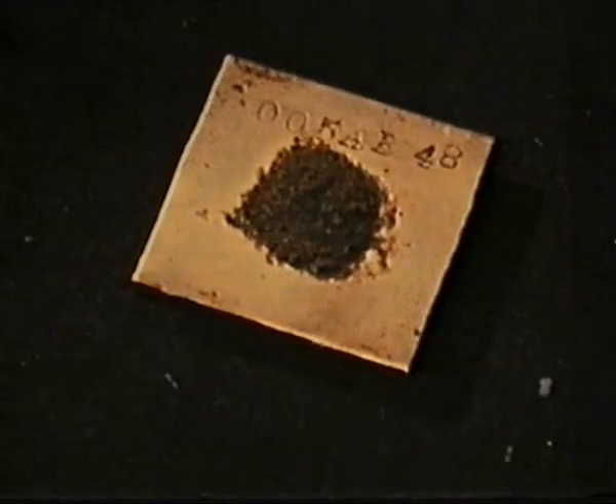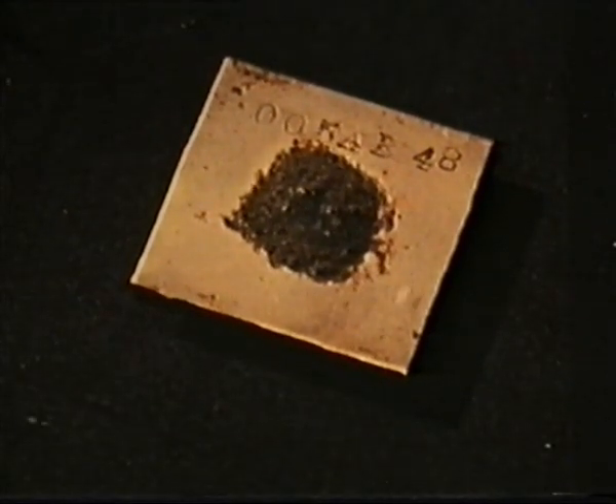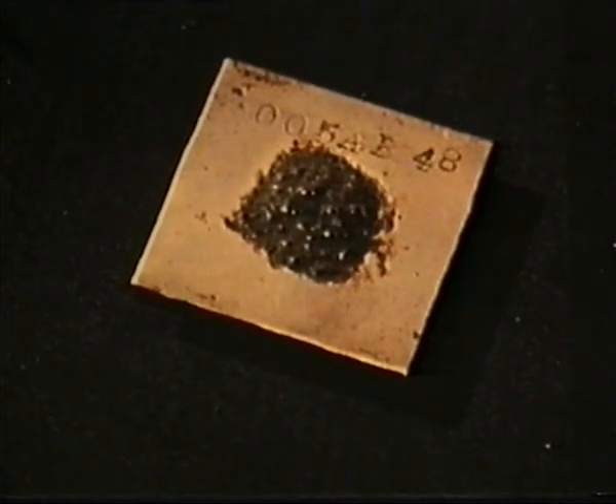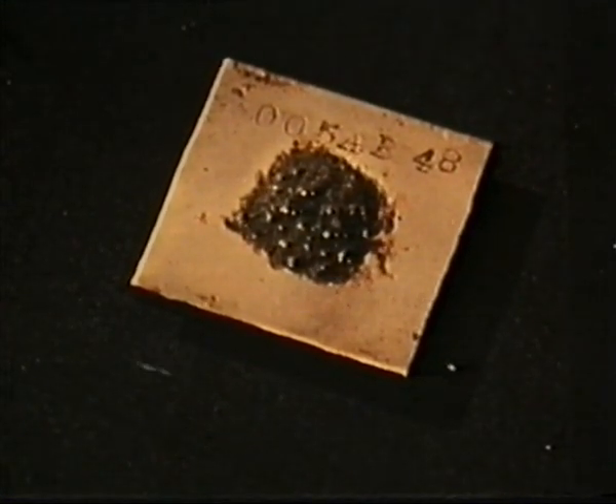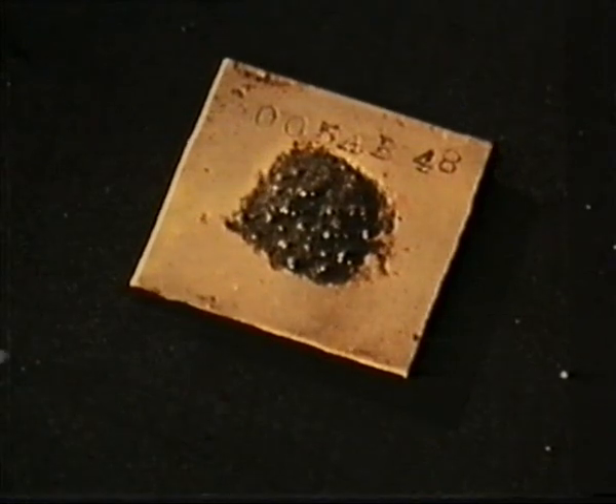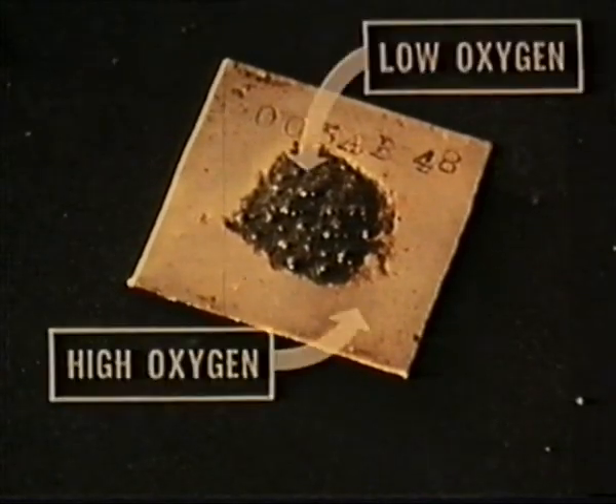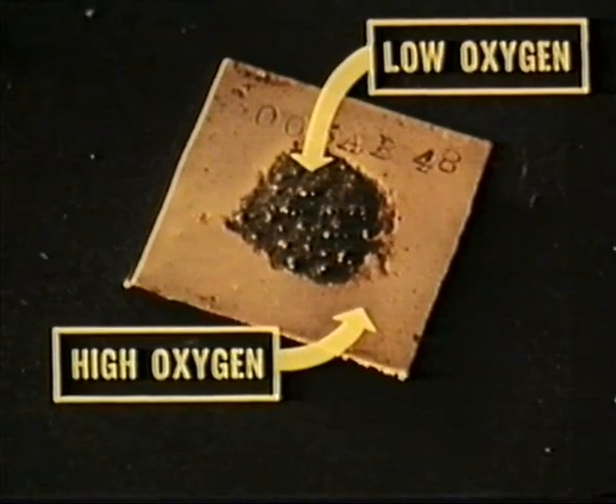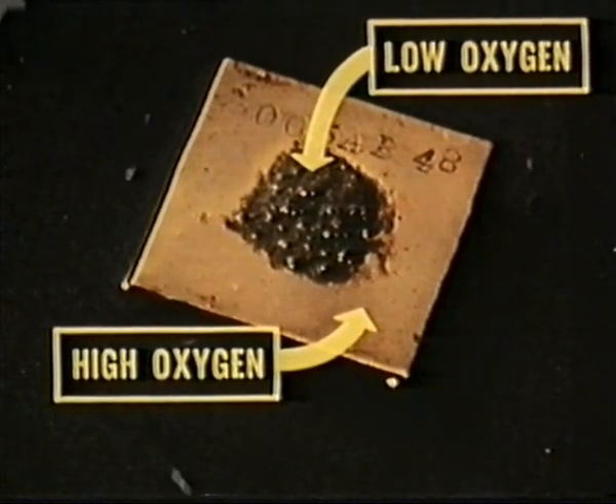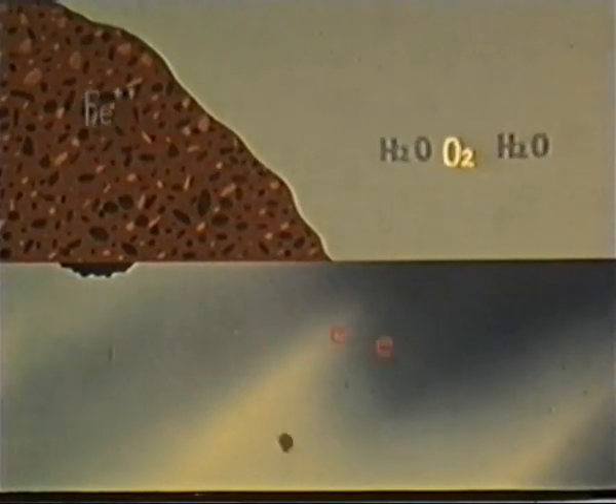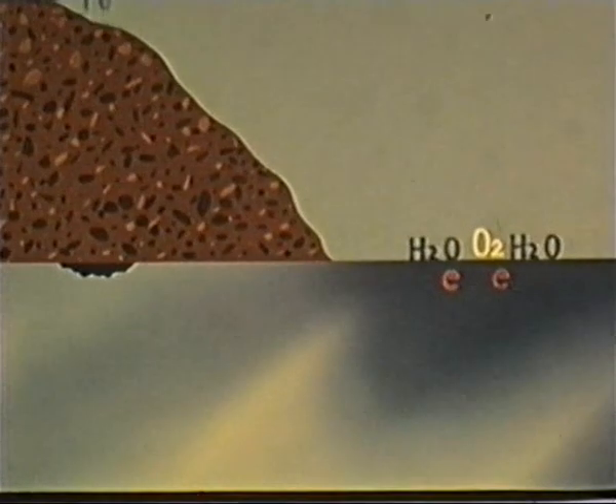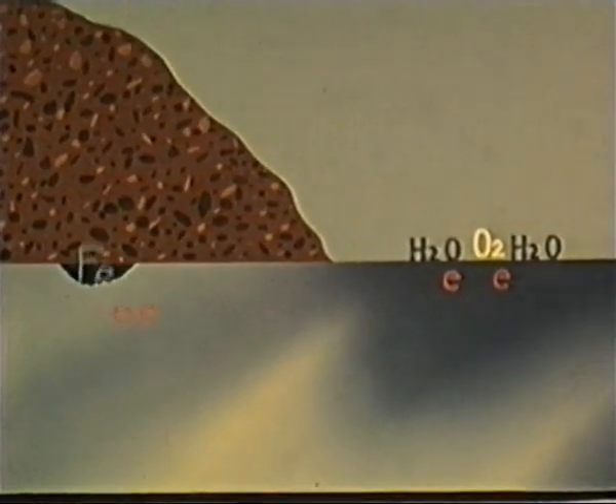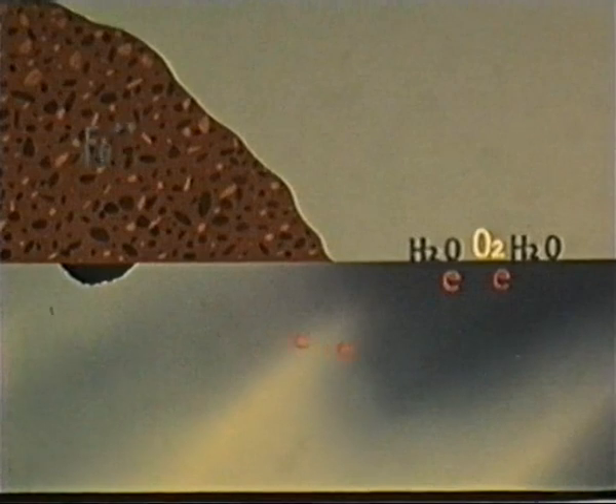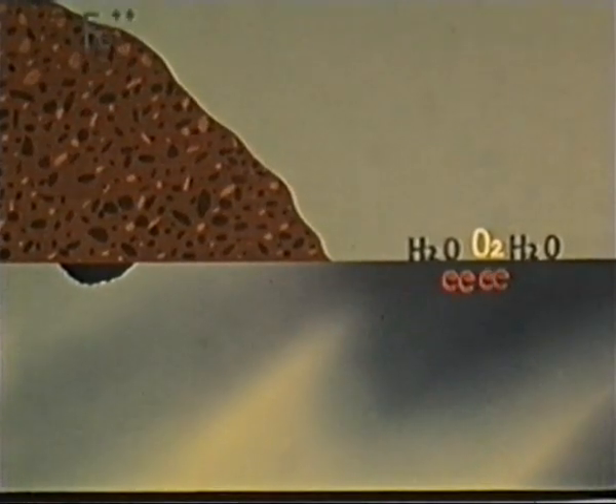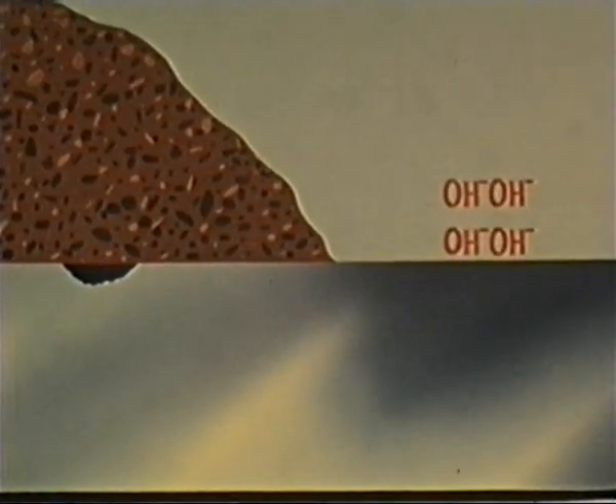Most frequently, the conditions that give rise to oxygen concentration cell attack are associated with the presence of a deposit at one point on an otherwise freely exposed surface. The metal outside the deposit will be readily accessible to oxygen, while that under the deposit will be shielded from it. This will set up a corrosion cell with the formation of metal ions in the anodic region under the deposit. Electrons will flow through the metal to the surface outside the deposit, and a cathodic reaction there will result in the reduction of oxygen to form hydroxyl ions.